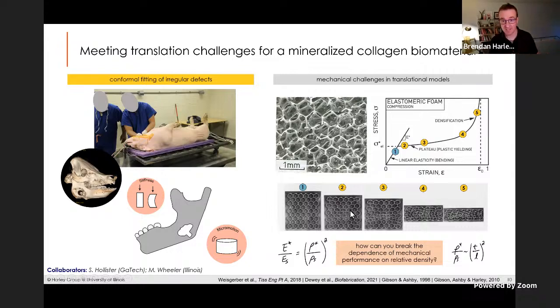And you see that in this point too, where you start to see what's known as the strain band, a region where the pores start collapsing. And as soon as one pore collapses, the one next to it collapses and it cascades, you get these strain bands that form. And since everything's collapsing, you put just a little bit of load and get a huge amount of displacement. The material collapses on itself. And eventually you get to the point where all the pores are lost and you get what's known as densification. So all the pores are lost and now you have the solid material pressing on itself and the slope goes back up.